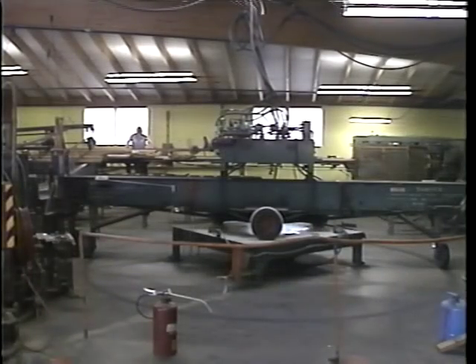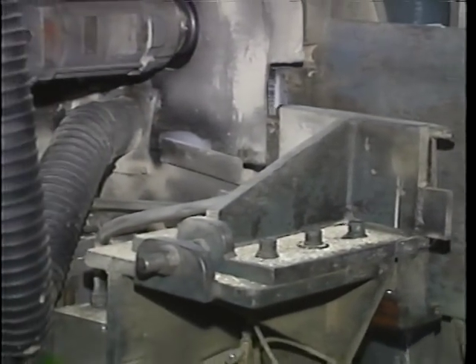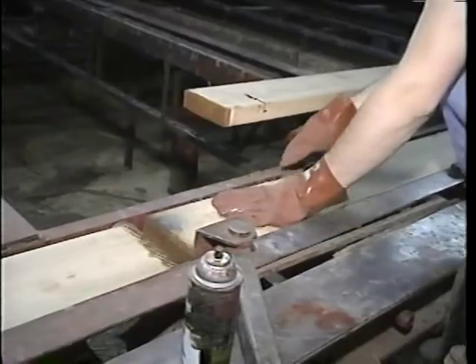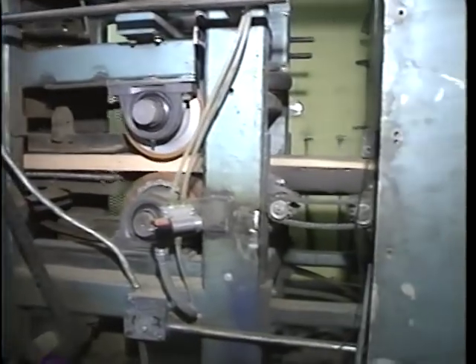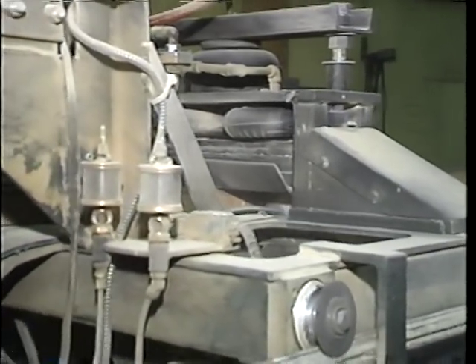The actual fabrication of the individual laminates into beams or deck pieces begins with boards loaded into a turntable conveyor. The turntable positions the board against a locking plate, and it is finger jointed and coated with industrial adhesive — the glue — at both ends. The pieces move to a conveyor belt where individual pieces are joined, then moved along the conveyor under a radio frequency dryer — what the plant personnel called a microwave for wood — and then the boards are cut into ordered lengths.